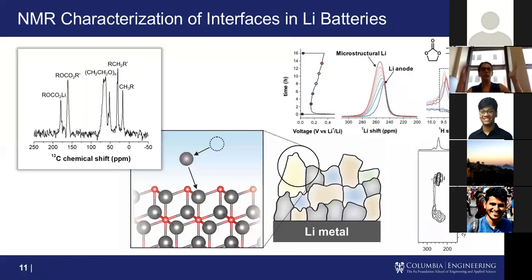So how do we actually go about figuring out how any of this stuff works? Our favorite tool to use in my lab is something called nuclear magnetic resonance. It's very similar to an MRI that you could get at a hospital. But instead of always looking at an image, we can also look at the spectroscopic signal of individual molecules that are on the surface of these lithium metal anodes. We can also still take an image. This is showing a lithium cell where we have just two strips of lithium, and we've grown some dendrites to connect them together and intentionally short circuit the cell.